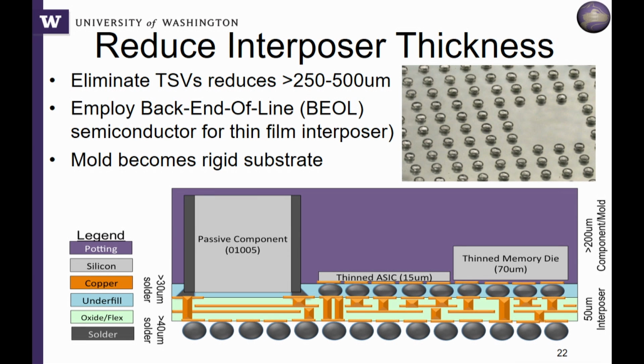In fact, our first few attempts at this, we spent 6 months doing this. We got our samples done, and everything looked good. We put our stencil solder balls on top of our sample, so the bottom of the chip in that picture is the last step. We stuck it in our traditional reflow oven and heated up that plastic substrate. It warped, and all our solder balls ran all over and shorted and bridged, and we lost 6 months of research.